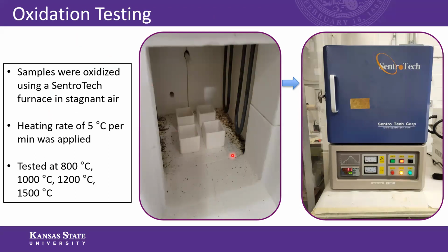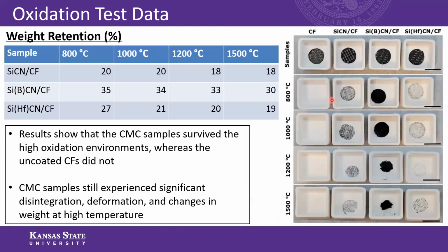So this is an image of how the samples would be placed into the box furnace. And the results are as follows. The results show that the CMC samples survived the high oxidation environments, whereas the uncoated carbon fiber itself didn't actually survive any of the 4 oxidation tests. However, even though these CMC samples did survive, some significant disintegration, deformation, and changes in weight were shown at high temperatures. As you can see visually, the CMCs look very much different from when they began at all temperatures.